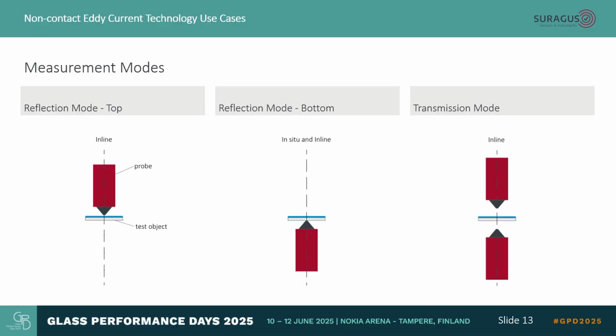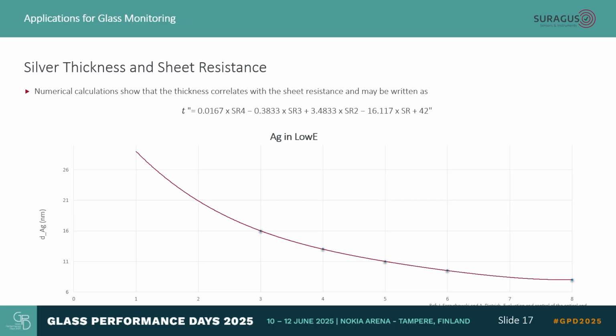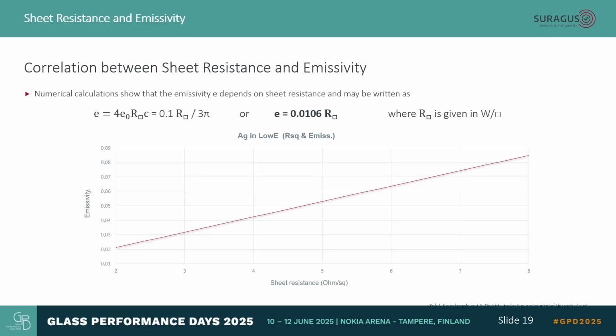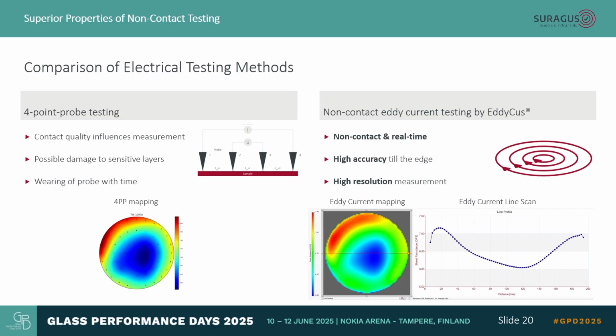And the key for the architectural glass industry is that the sheet resistance correlates with the silver thickness. That is basically one aspect. The other aspect is that the sheet resistance correlates with the emissivity. So emissivity is also one core aspect that we take care of. Another testing method for this sheet resistance is the 4-point probe method, which is a contact method, and which gives the same results but has a lot of disadvantages.